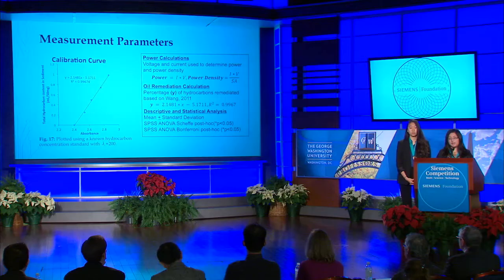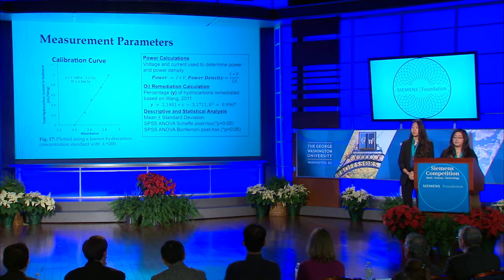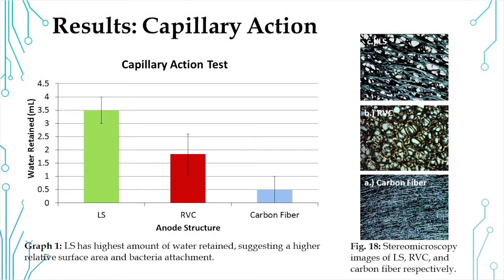For the oil remediation, we used a method based on Wang and a calibration curve to determine the amount of hydrocarbons remaining after the 10-day period. All our data was analyzed for statistical significance as well. The capillary action test showed that the loofah sponge retained the most water, indicating it has the highest relative surface area. The SEM results that we took supported the capillary action test.